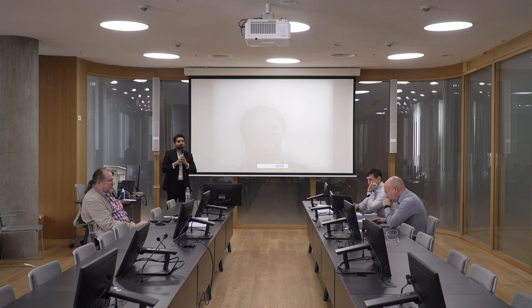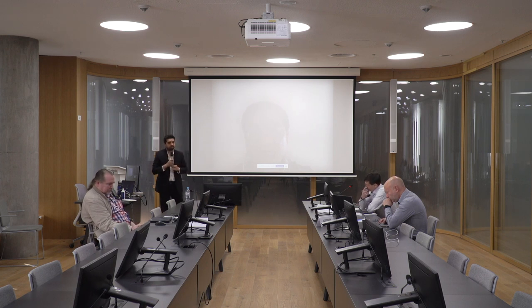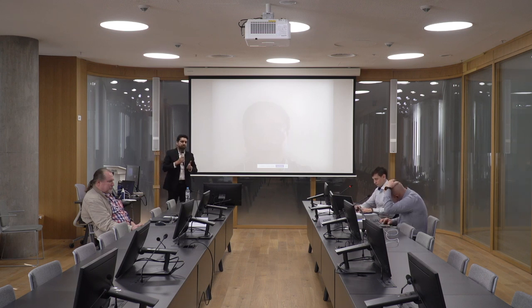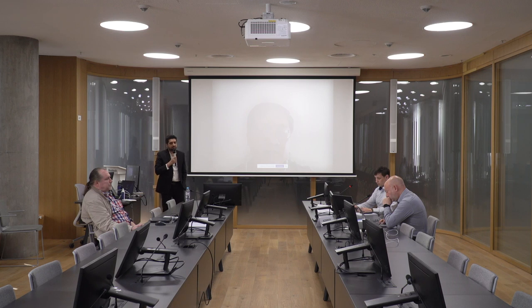So I feel that when I did that research, I should go to a single 2D material that will have a single interface, rather than random multiple interfaces. That was also suggested by Professor Chang Chung, that you should focus on a single material. So that's why I use graphene, and then I can use different ways of aligning or orienting in one direction, and then you can self-assemble. In this way, you can enhance the propagation of heat and make conductive channels, and you can have this increase in conductivity. So in this case, approximately 5.1 watts per meter Kelvin at 10 weight percent, I think it's a good result. Thank you.